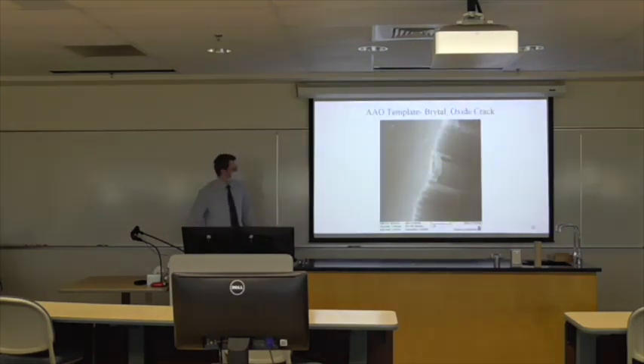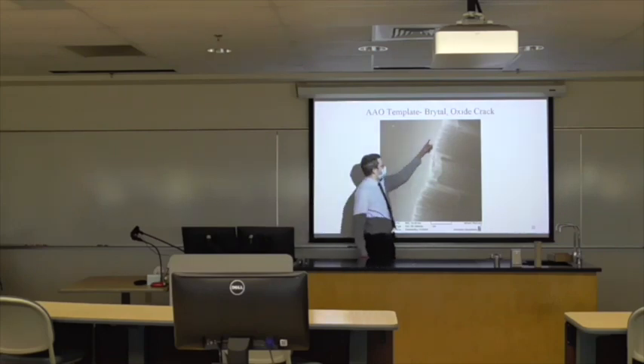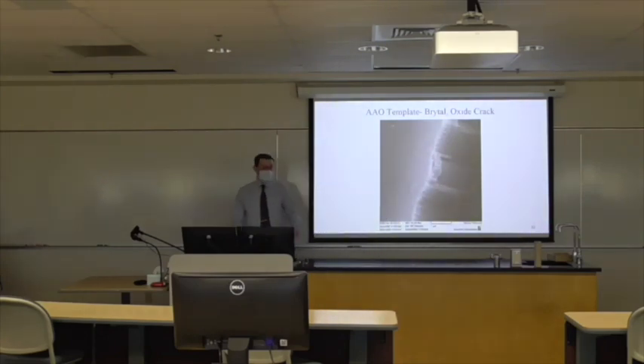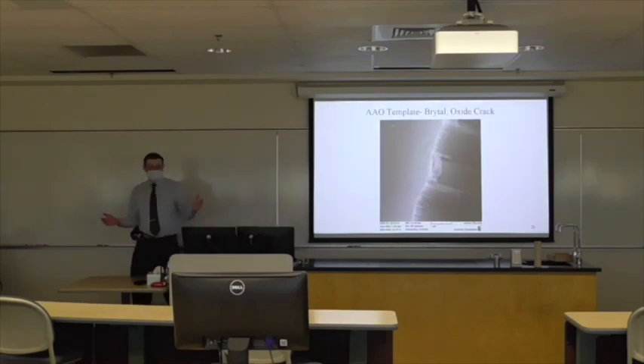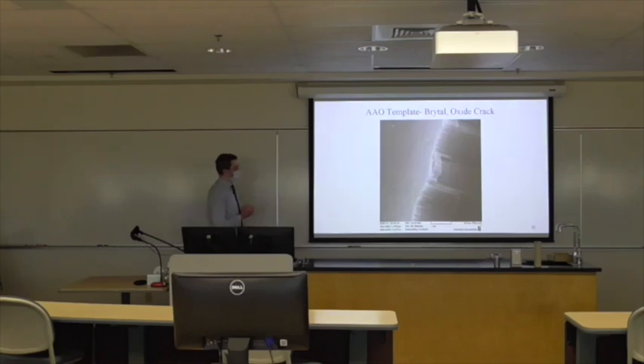One interesting thing that was relatively serendipitous is that there was a crack in the oxide layer of the aluminum oxide template that was made with the Brytal electropolished piece of aluminum. And what we can see here is not only are there still these pores that exist, but they extend vertically through, as you had also seen from the Masuda and Fukuda images that show that vertical extension of the pore throughout the aluminum oxide layer. So this is great. We were able to produce these templates that exhibit the same structure that we're looking for.